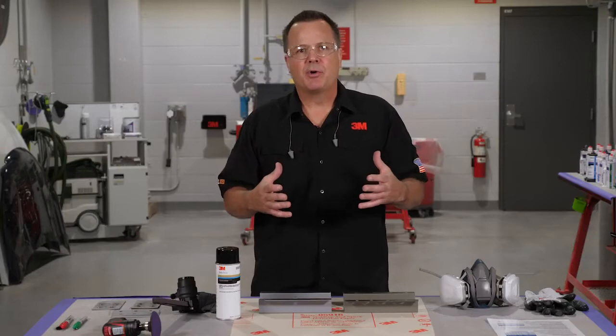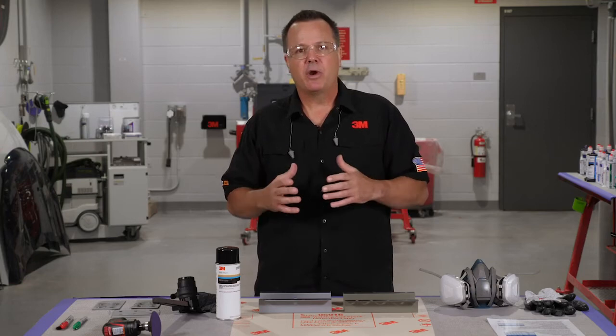The name weld-through primer really is a misnomer. It's not really a primer, which we've discussed, but also we should not actually weld through or right over the top of weld-through primer. It's considered a weld contaminant. And actually, if you look at a lot of the OEM statements, they will actually specify to clean it from the weld zone before welding. We only want to be welding on clean bare metal. So one of the first things we need to do after it's applied is to remove it from the immediate weld zone, and I'm going to show a demonstration on one of the best ways and easiest ways to do that.